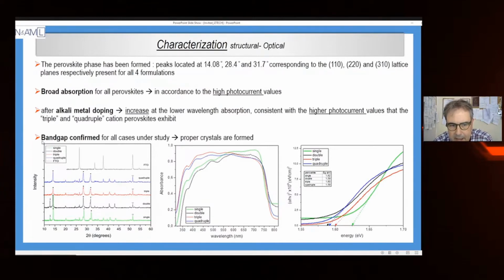Finally, the band gap can be confirmed, of course, with diffuse reflectance measurements. And you can see here that the band gap of these materials is close to 1.5 eV, or a little bit higher or a little bit less. So from the energy gap, we can realize that we can sensitize these solar cells in the whole region of visible light.